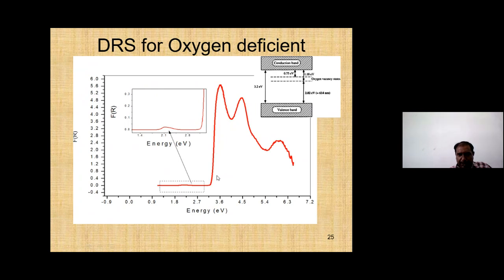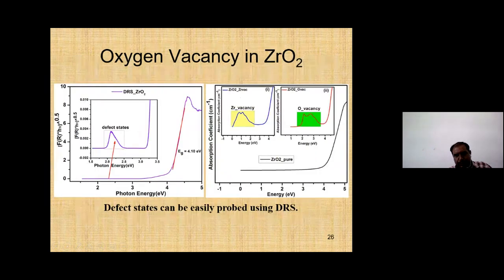So the thing is that when you perform the diffuse reflectance spectroscopy experiment, you can essentially find out the states which are due to the defects present in the sample. Now if you look at the quantitative value of this absorption here, it's very small. So it means that the amount of defect is really small as compared to the actual band. These are the defect states present in the sample, and that is also reflected in the optical absorption spectroscopy. Okay, so in fact, what you can do is the following.